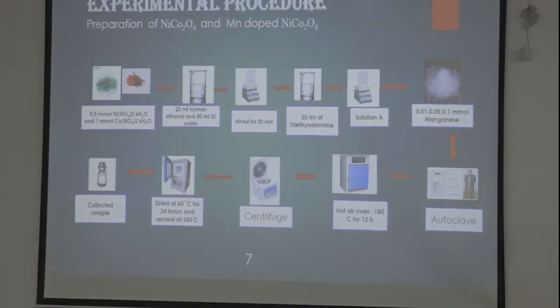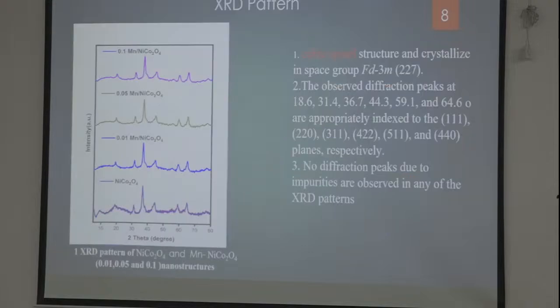These are the XRD patterns for nickel cobalt oxide and three different ratios of manganese doped nickel cobalt oxide. I get a cubic spinel structure with Fd-3m space group, and there is no diffraction peak due to impurities observed in any of the XRD patterns.